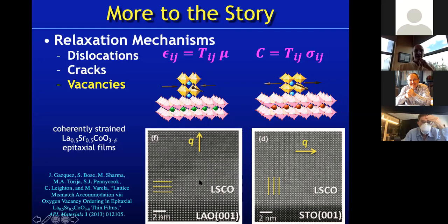On the left-hand side, by putting this on a smaller substrate, again, those planes of oxygen vacancies exist, but their orientation has switched to make it so that overall it has a lower energy to go on this substrate. So this is going to make it so that it's smaller in plane. This makes it bigger in plane. So this makes it better match to the substrate and reduce the elastic energy.